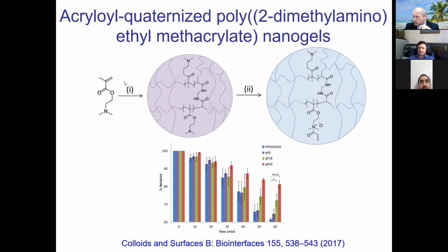So we prepared nanogel particles from copolymerization of 2-dimethylaminoethyl methacrylate. And then we functionalized them by reacting with acryloyl chloride. And we have conducted a series of physical chemical studies to characterize the particles. And we also looked at retention of these systems on ocular surfaces. So the graph at the bottom shows how they are retained on the surface. So if we have the quaternized particles, or how we call them quaternized, the particles that were modified with acryloyl chloride, then we could improve mucoadhesiveness significantly.